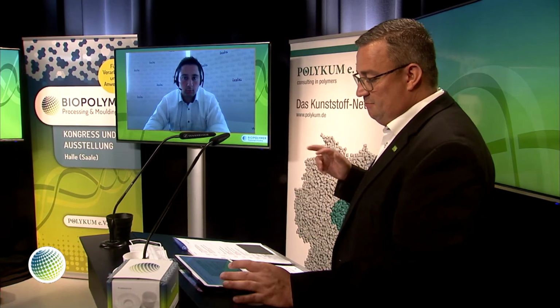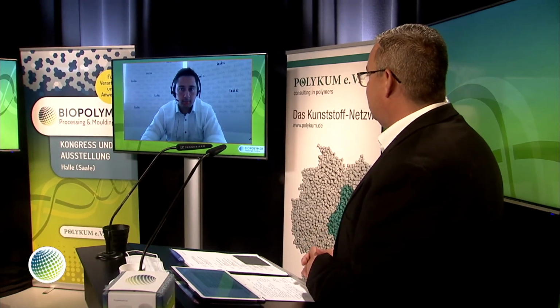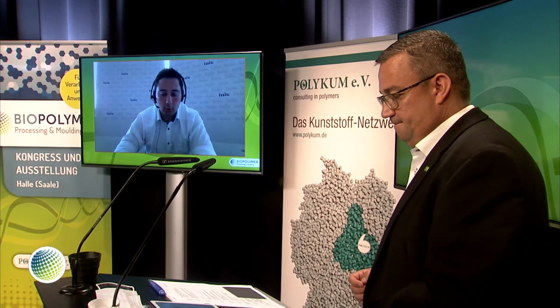I'm asking a question, stepping a step back, regarding the question, can the same thermoforming machine and tool be used? I understood the tool needs to be adjusted regarding the mold shrinkage, but how about the machine, apart from the heater you pointed out? What about the rest of the machine? Could the core thermoforming machine stay more or less the same to process biopolymers? Yes, I would say it can stay more or less the same. Maybe a few years ago, the PLA had the disadvantage. It was really brittle, and so we had to deal with it and solve the problem. We had the feeding of the film into the machine and out of the machine. We had to bring in a big radius so that it's not broken during the processing.